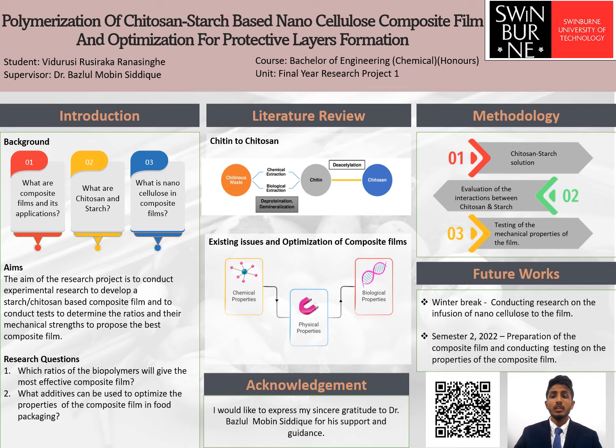Initially, the preparation of chitosan starch film would be the first challenge for my experimental research. According to the research so far, I will be making a chitosan solution of 2% concentration. This is prepared by dispersing 10 grams of chitosan in 500 milliliters of lactic acid solution of 1%. After dissolving the chitosan completely, the solution can be filtered using cheesecloth by vacuum aspiration.